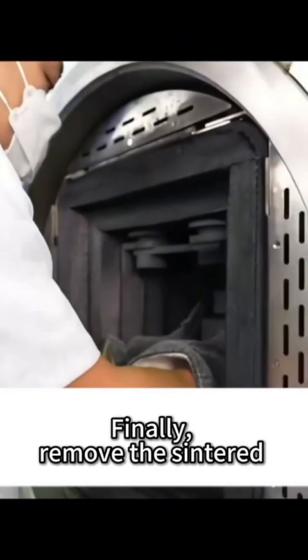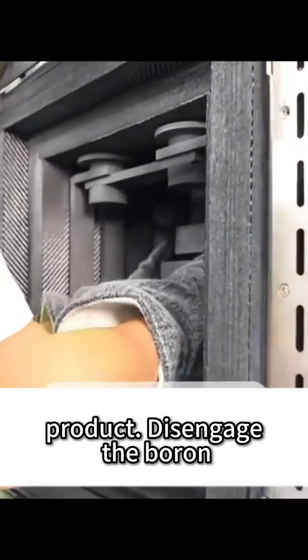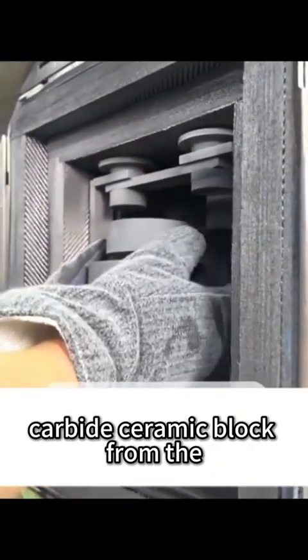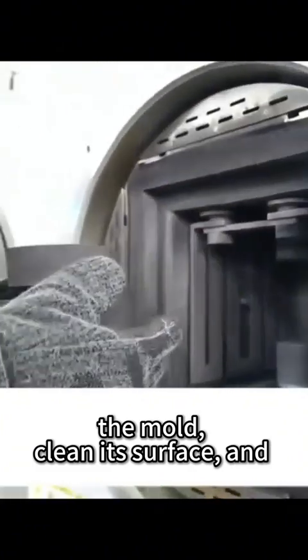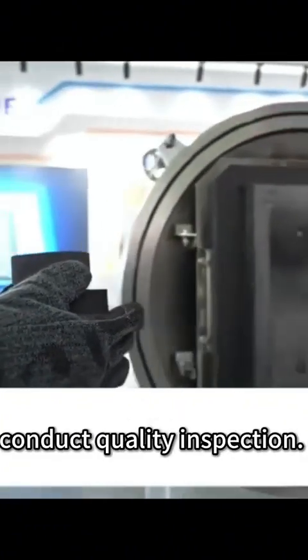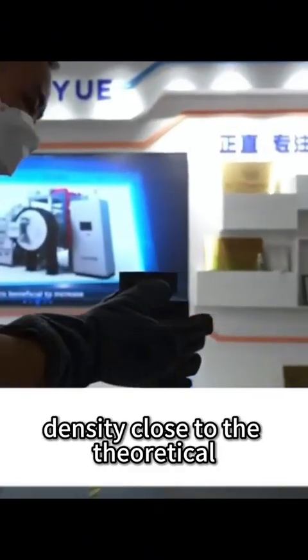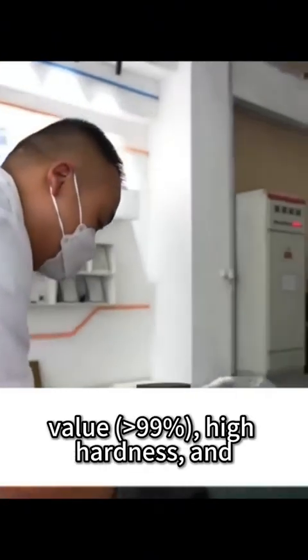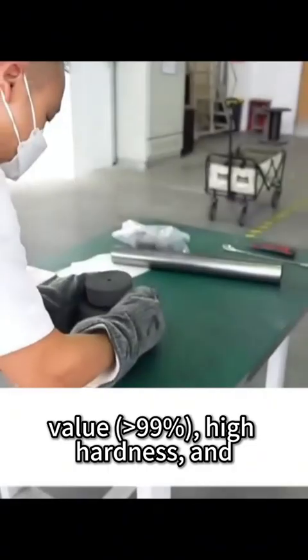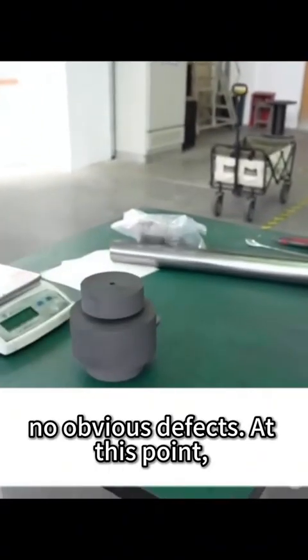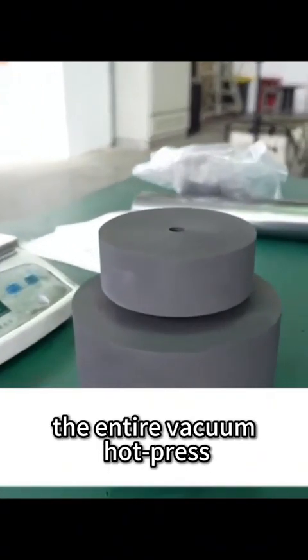Finally, remove the sintered product. Disengage the boron carbide ceramic block from the mold, clean its surface, and conduct quality inspection. The ideal product should have a density close to the theoretical value, 99%, high hardness, and no obvious defects. At this point, the entire vacuum hot press sintering process is complete.